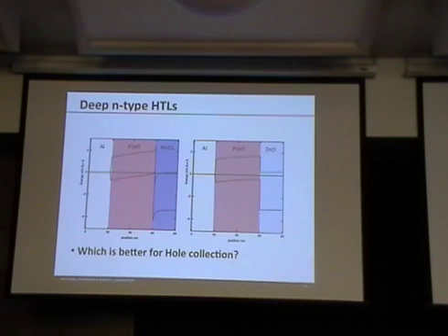I haven't worried about reorganization energy, what happens when a charge carrier moves from this polymer into this oxide, because they aren't the same. So there are all these additional energy terms that I would really have to consider if I wanted to understand exactly what's happening in the system. But at the end of the day, if I know enough about those different energies, I should be able to calculate a rate, and my contact could be viewed as selective, I would contend, if the rate for the charge carrier of interest, in this case holes, is higher than that of electrons.